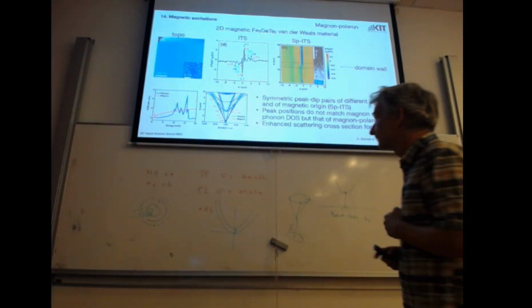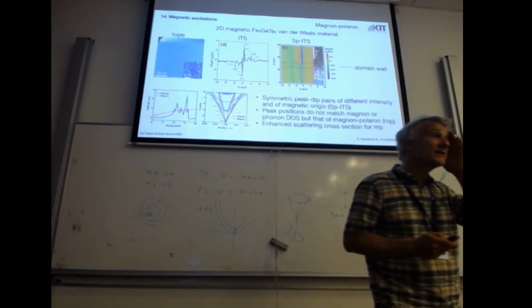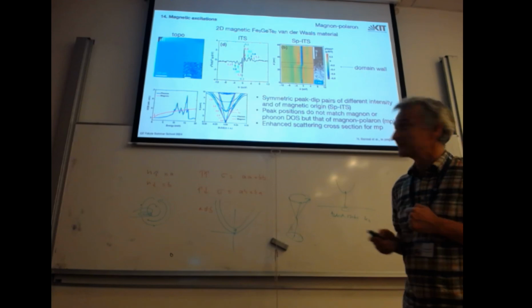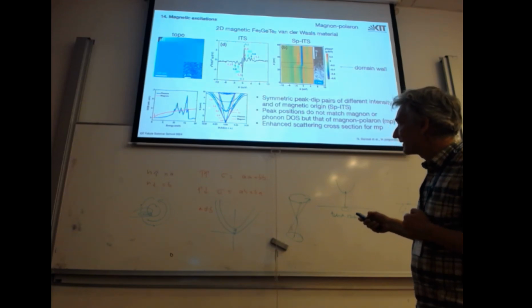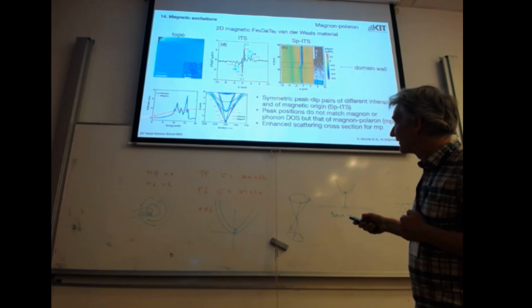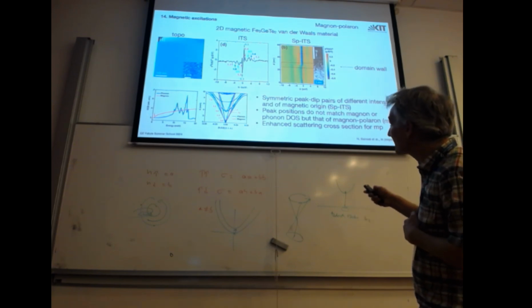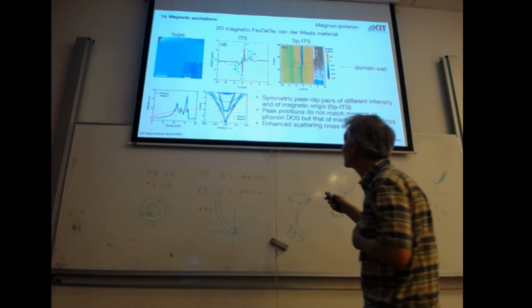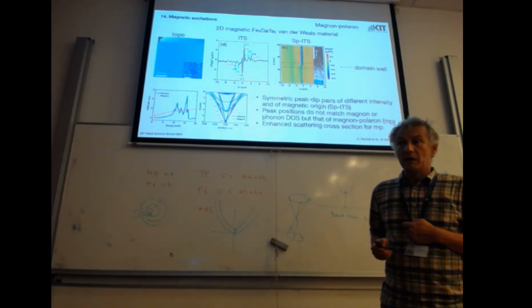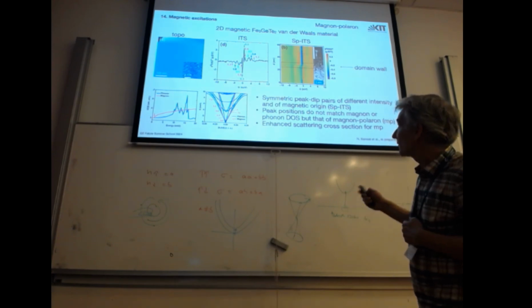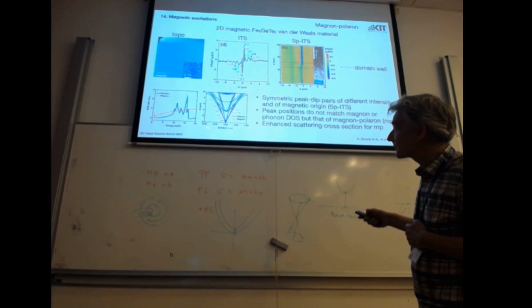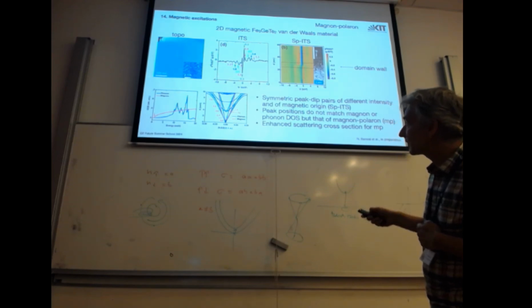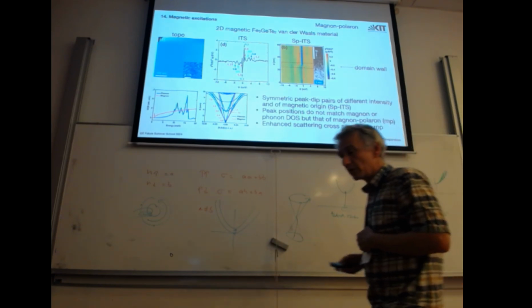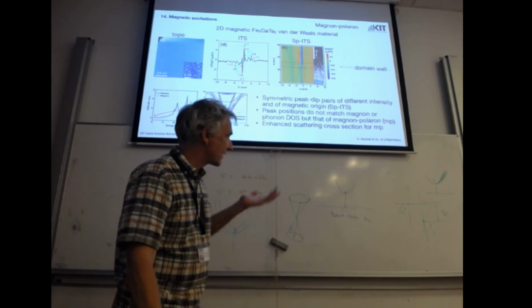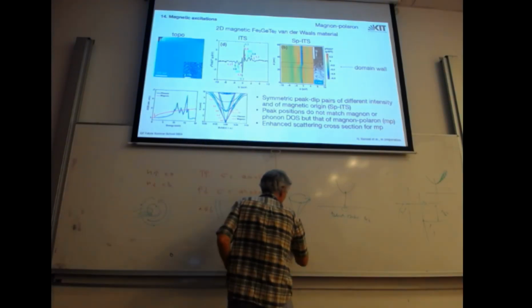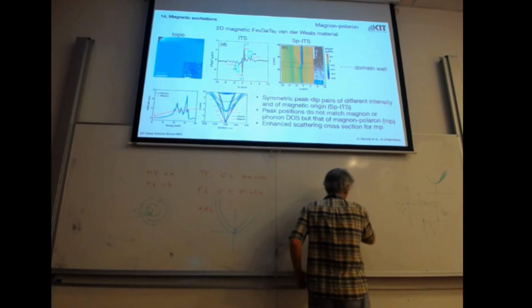So it can be a magnon. But you can calculate the magnon density of states in this system. It's the red curve. It's completely flat, smooth. There are no special points. There's nothing special about the density of magnons at these energies here. You can think of phonons. Let's assume these are phonons. And then this is the phonon spectrum. So also this does not match. This neither matches the phonon nor the magnon spectrum. What is happening here? And that's something special in two-dimensional systems.